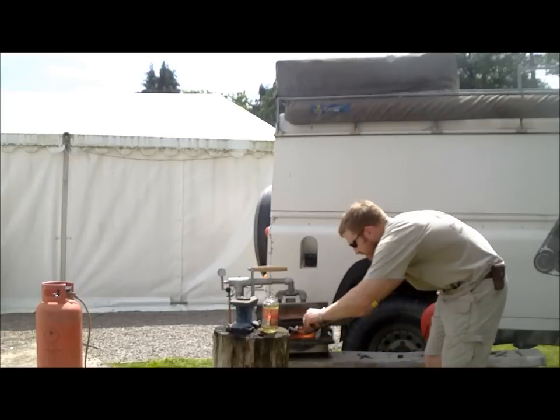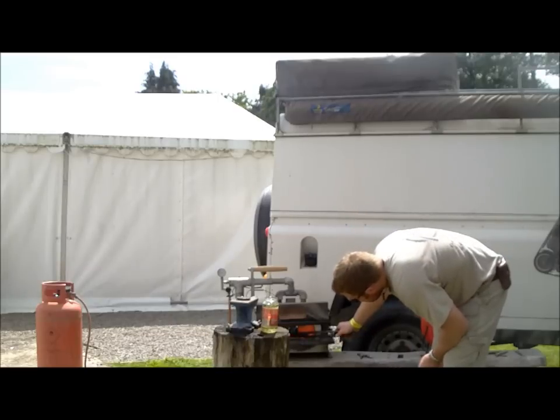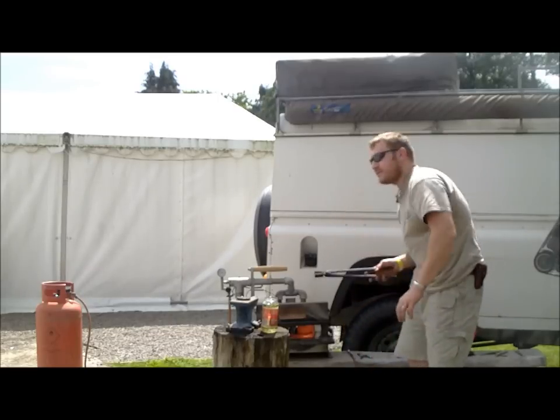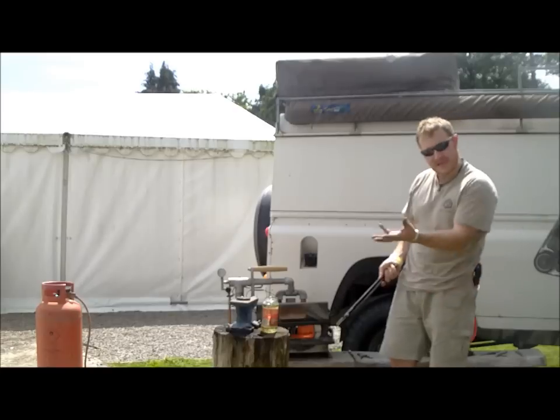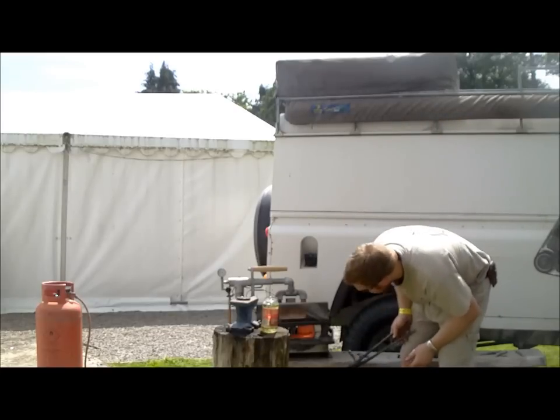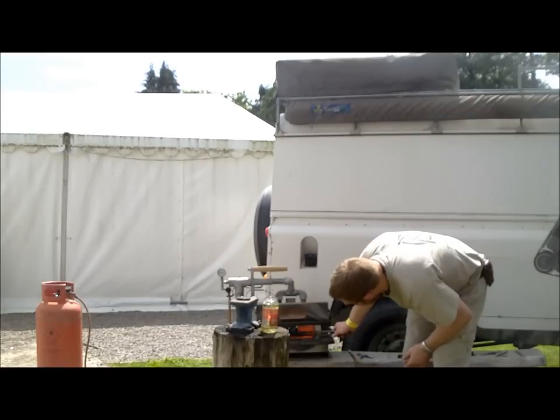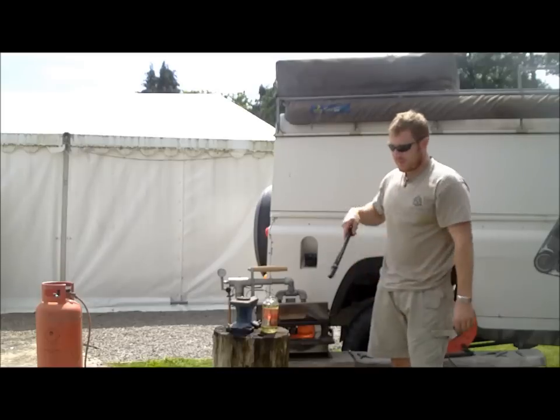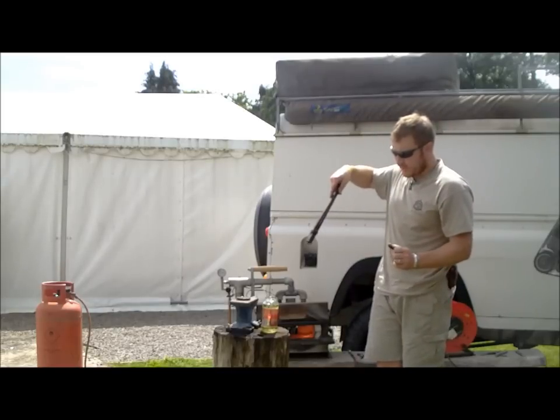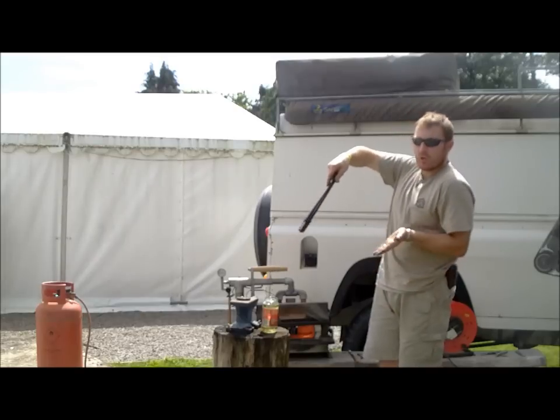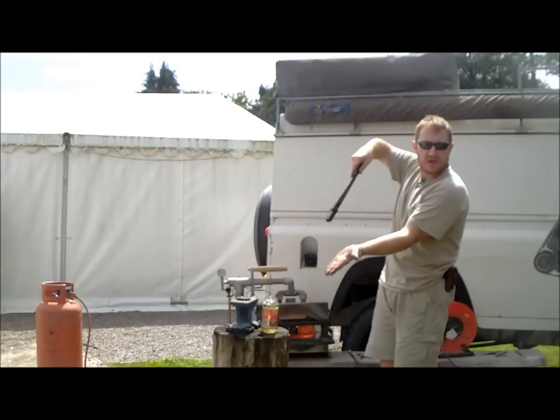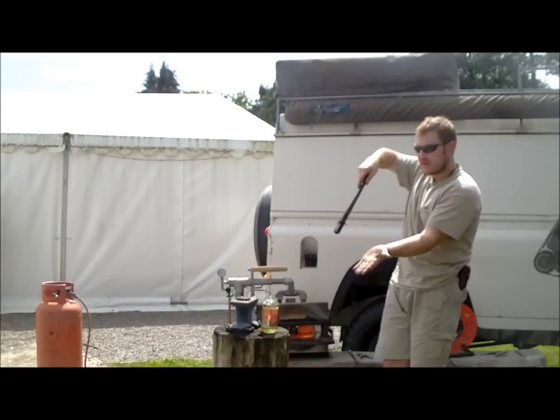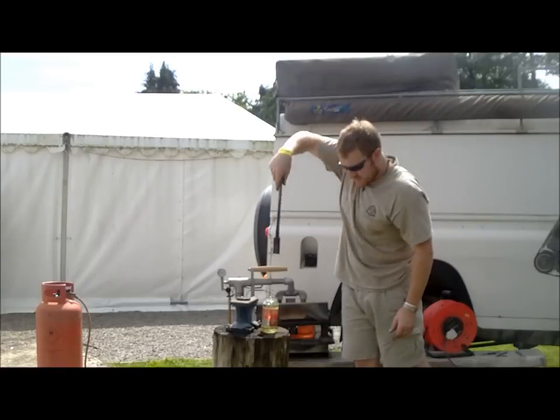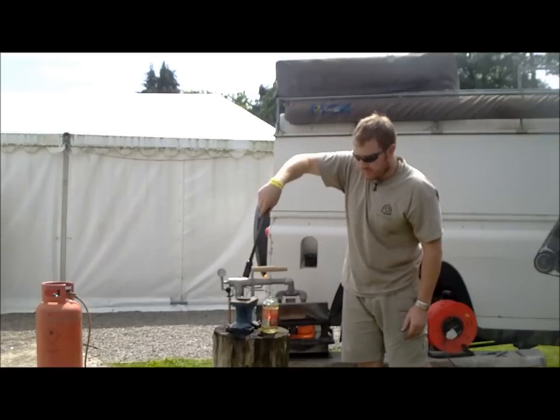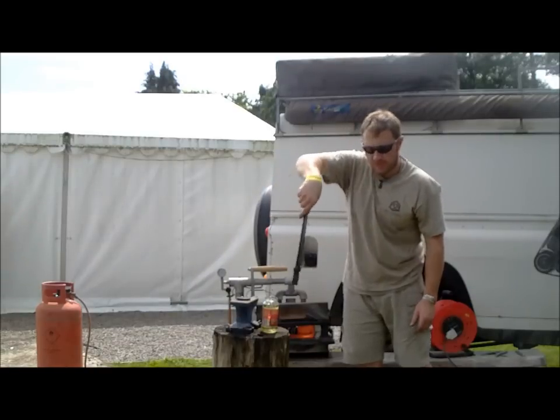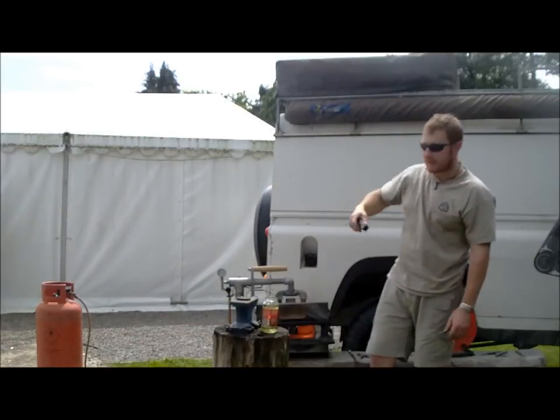So we've got it nice and red. It's no longer magnetic, so we normally test it and then I put it back in there and heat it back up to that temperature again. And when we dip it, and I've learned from experience the bad way, if you dip it in at an angle, one side of the blade cools quicker than the other and you make these beautiful crook knives. So you want to dip it as vertical as possible, and if you're going to move it in the oil, make sure you move it back and forth rather than just randomly. If you stir it round, you can distort it.